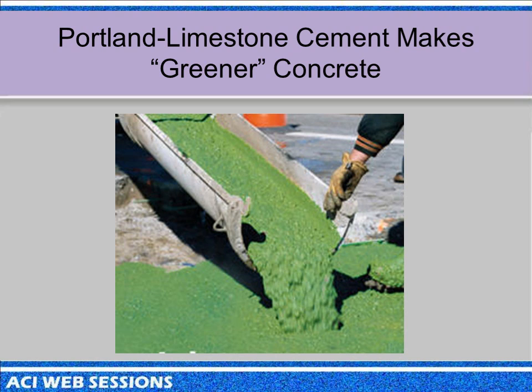Well, I understand the issue. I'm not sure how to address that. I mean, certainly with the limestone cement, you know what's in the cement that it comes, and you've got control on that. Now, the ready-mix guys, if they start adding fillers, you can blow your optimum. The reason we picked 15% as opposed to the 20 the Europeans adopted was we found reduced performance when you got up to that level. And so between 10 and 15 seemed to be optimum in terms of not seeing the effect on concrete properties.